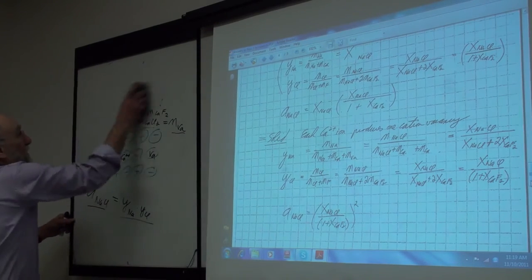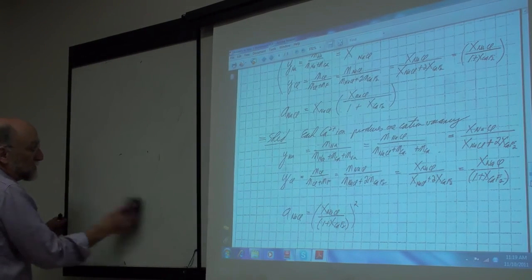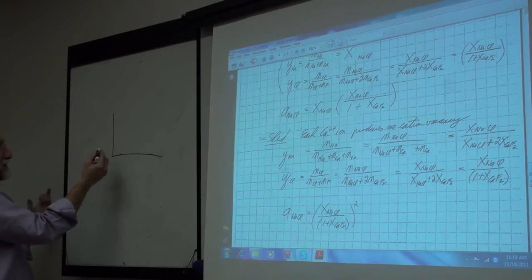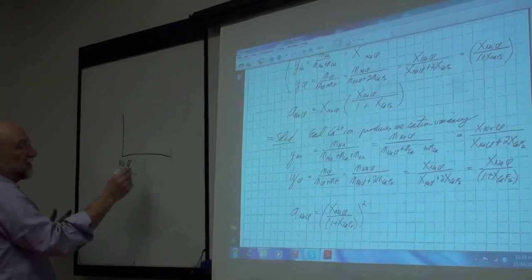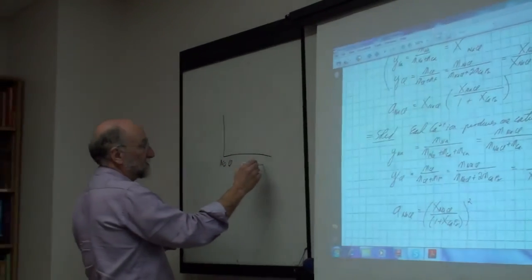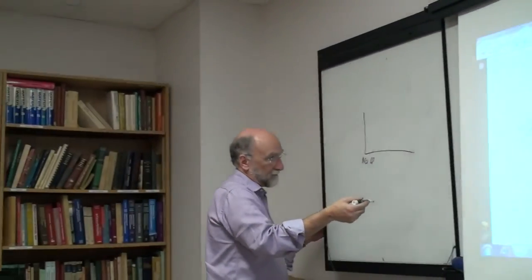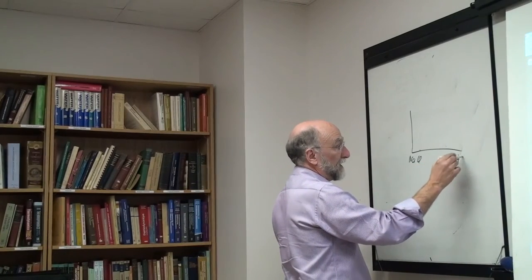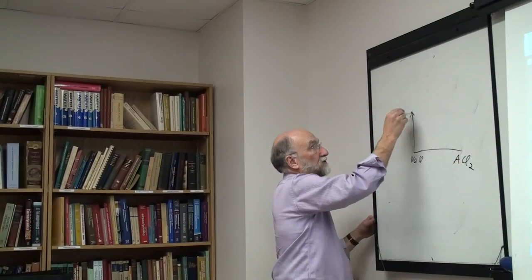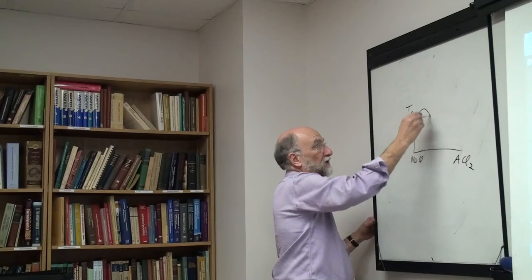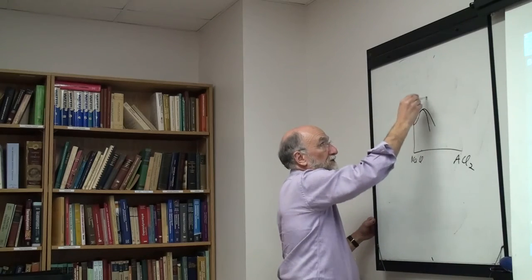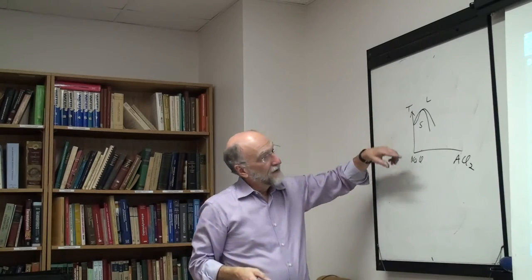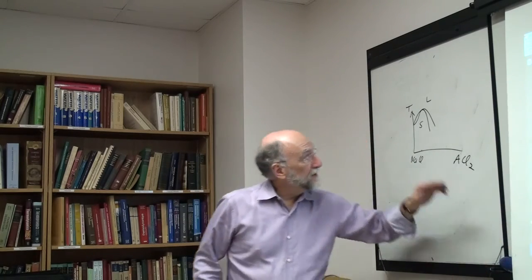And as I showed you another example then, what this would do to a phase diagram, talked about this before too. If you had here, say, sodium chloride, and you're adding something like calcium chloride, you're adding ACl2 versus temperature. This will give you a phase diagram that tends to have this is liquid and this is solid. The reason being that the solid has a higher activity than the liquid.